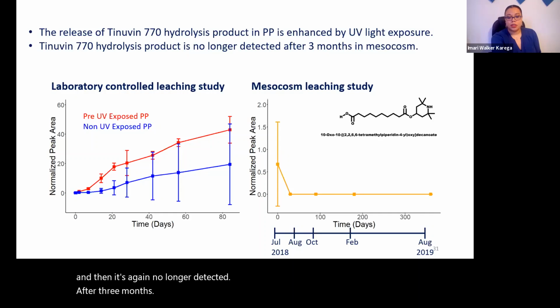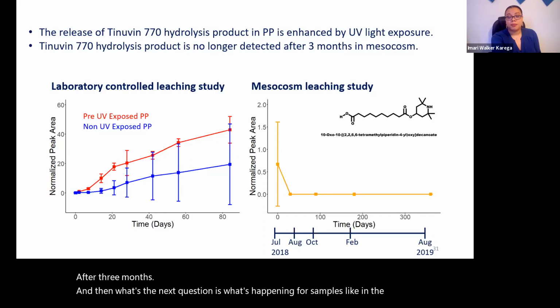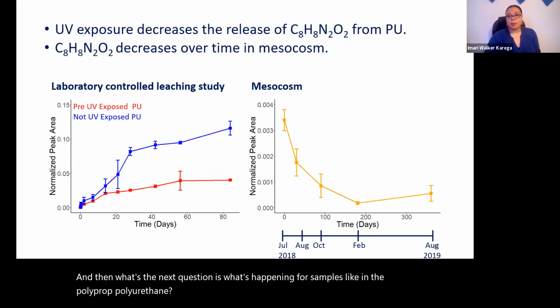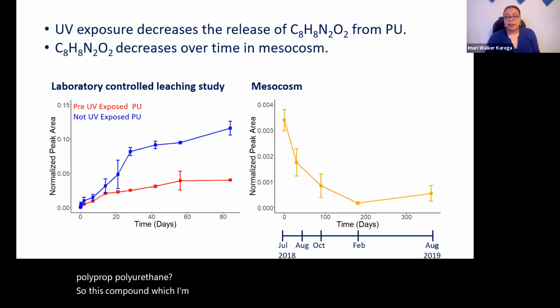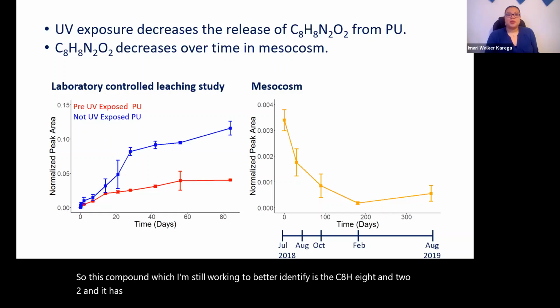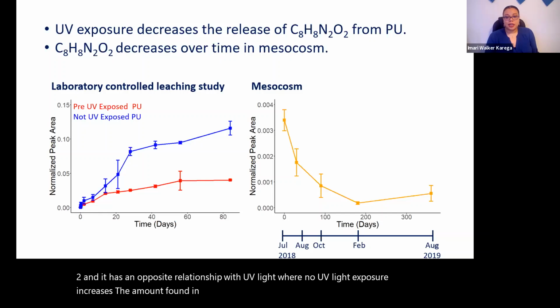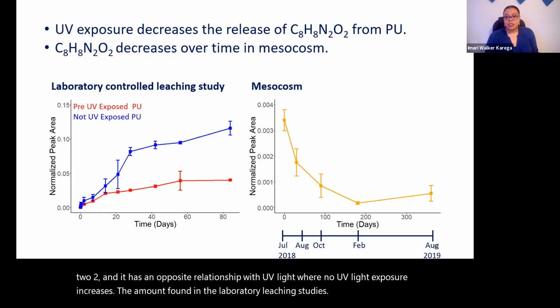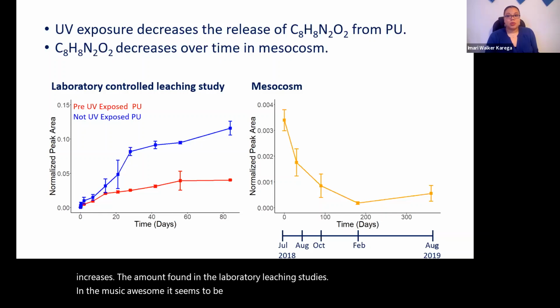The next question is what's happening for samples like in the polyurethane? This compound, which I'm still working to better identify, is C8H8N2O2, and it has an opposite relationship with UV light, where no UV light exposure actually increases the amount found in the laboratory leaching studies. In the mesocosm, it seems to be steadily present throughout those 12 months, but decreasing over that time.